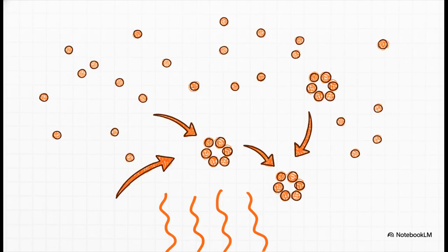And that brings us to the final, and I'd argue the most important step, aging. Now we take our supersaturated alloy and we gently reheat it, but to a much, much lower temperature. This isn't about dissolving anymore, this is all about control. This gentle heat gives those trapped copper atoms just enough energy to start moving around, but only a tiny bit. They start to cluster together, forming these incredibly small, perfectly structured particles right inside the aluminum. This is where the strength is actually born.